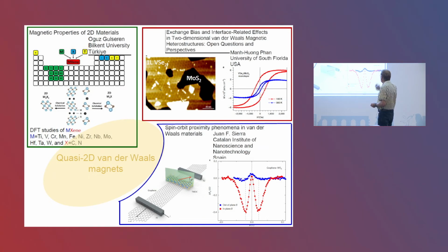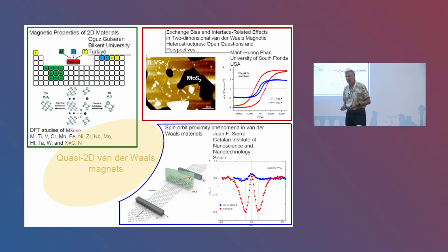But there were also really a series of interesting experimental talks. One of them, a talk today, an overview given by Manh-Huong Phan on the exchange bias and on the interface-related effects in two-dimensional van der Waals magnetic heterostructures, which is important in two aspects. One important aspect is the generation of this exchange bias. That means the shifting of the hysteresis curve in the desired direction with regard to the zero magnetic field. This is important, say, for memory storage devices.